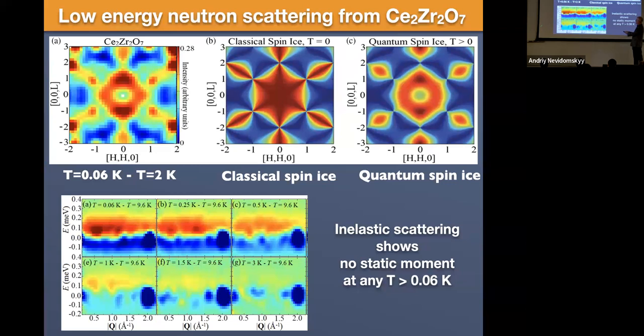Okay? And so we can integrate this up in energy and look at its Q dependence, look at its momentum transfer dependence in a neutron scattering experiment, and we get this result here. So this is unpolarized inelastic scattering giving us a structure factor. And the structure factor is diffuse scattering. There's no Bragg peaks here. There's not even elastic scattering here for that matter.